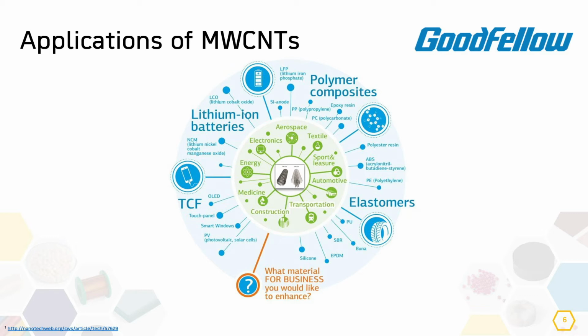Also, the electron transfer capabilities of these carbon nanotubes are giving them their ability to be used in electrodes. So, an alternative to graphite electrodes, for example, because graphite is usually used in electrodes in lithium batteries. Also, electrical properties such as conductivity and the sharpness of their tip. It is very well known that the smaller the tip's radius of curvature, the more concentrated electric field we will have, and the higher field emission we will also have. So these materials are used for field emitters